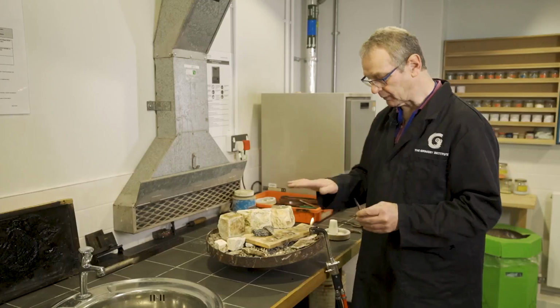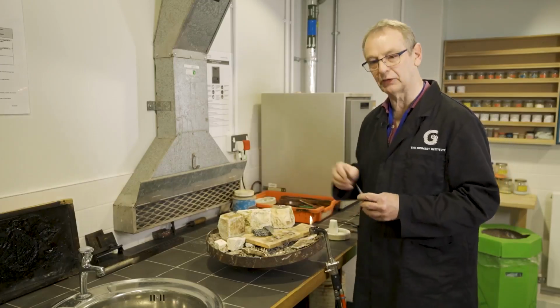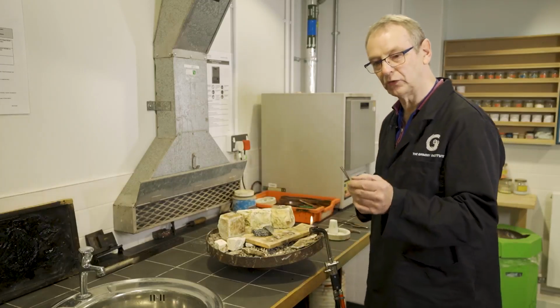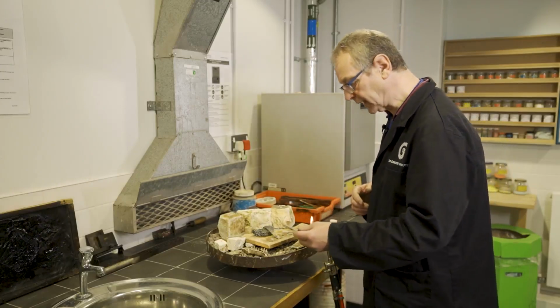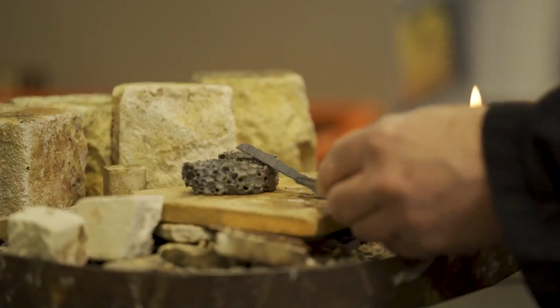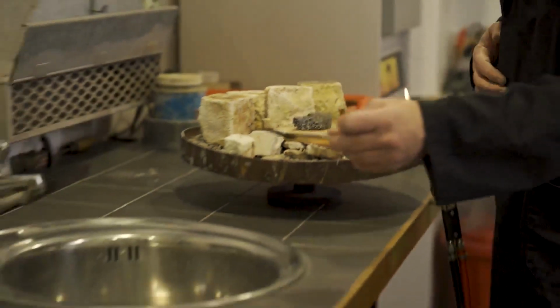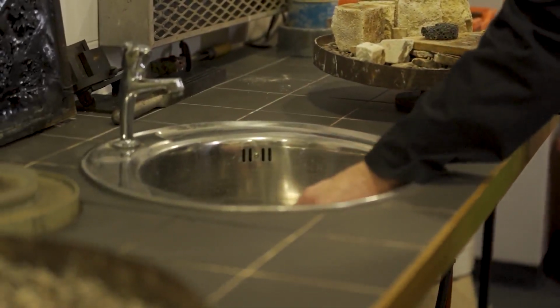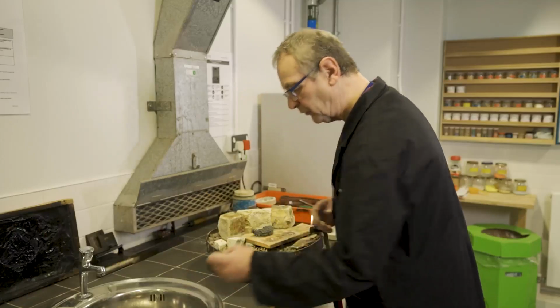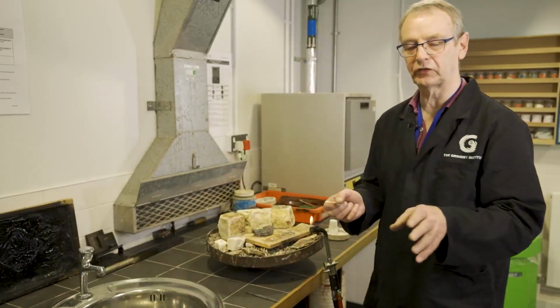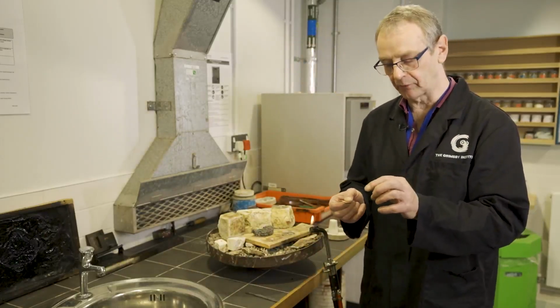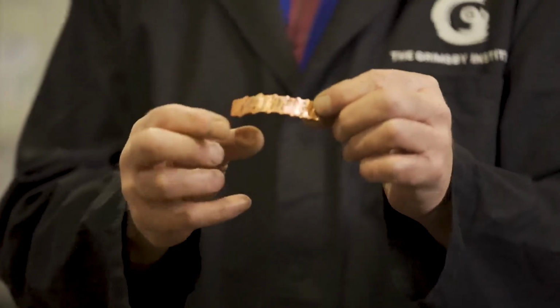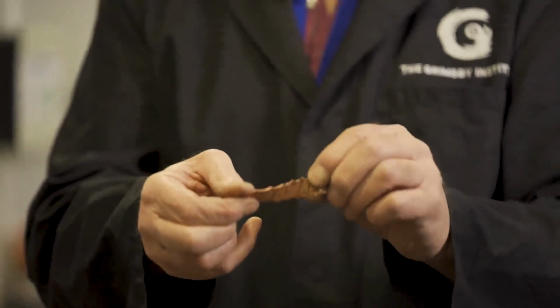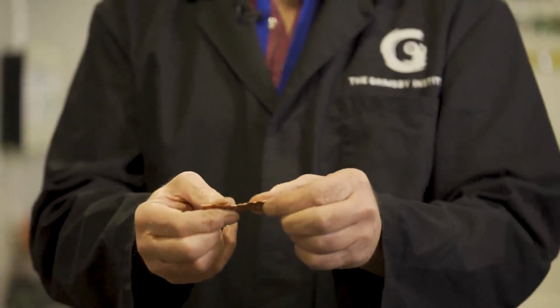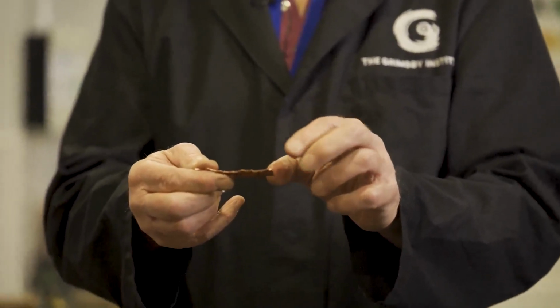and switch the torch off. Now remember, everything around here is very hot, so we're going to use tweezers to pick up the metal nice and carefully, and then straight into the sink, and that cools down. Because it's a really good conductor, it cools down very quickly. But now we can see this is so bendy and it's almost like a piece of chewing gum because we've taken the stresses and strains out.